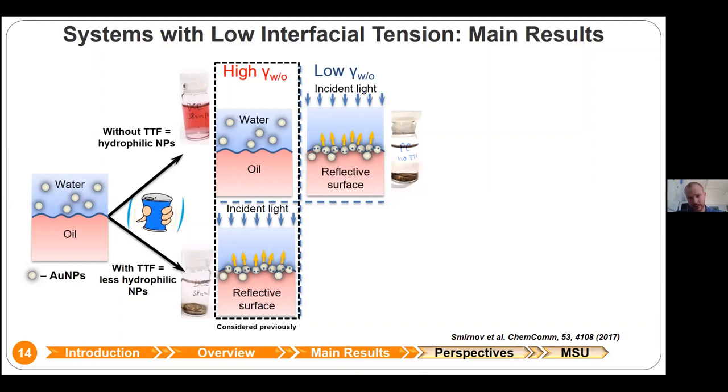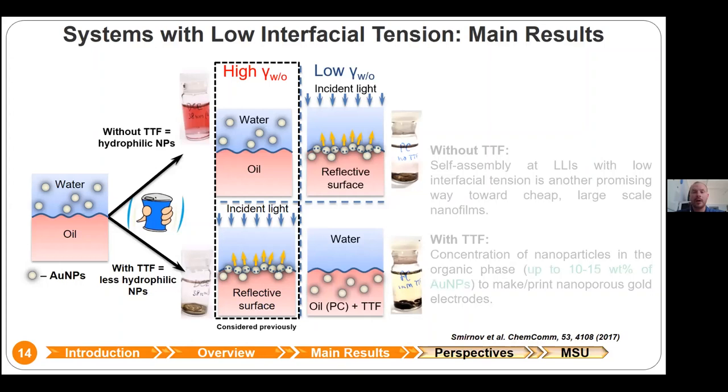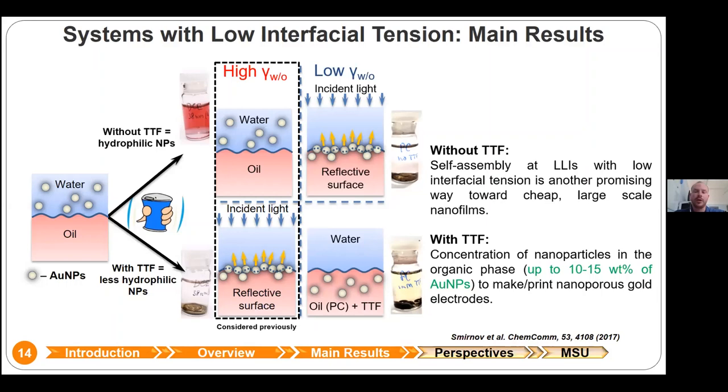But if we add the TTF, then nanoparticles suddenly transfer to the oil phase. In this case, this is PC, propylene carbonate. And in principle, we can use this technique to concentrate nanoparticles up to 10-15 weight percent and make kind of like ink for inkjet printing a porous gold electrode. And this is possible. Of course, at some point we were shocked by this behavior because it was not what we expected. And we started to investigate